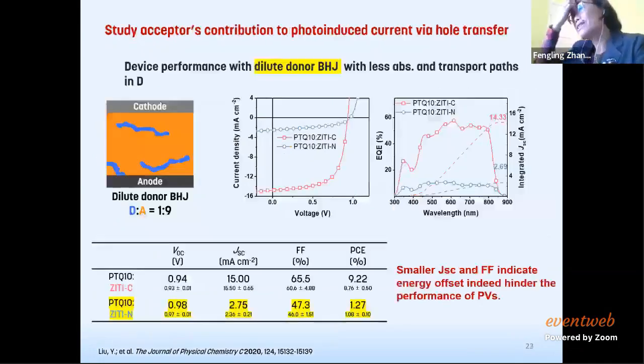So then we try to understand how the acceptor contributes to charge generation via hole transfer. Therefore, we make a device. Actually, we wanted to make a bilayer device, but the student in Beijing told us it's not possible with solution processing, because the top layer will dissolve the bottom layer. Then we thought, okay, if we can't make a pure bilayer device, maybe we can make a dilute donor device to decrease the impact from the donor and amplify the contribution from the acceptor. So it's closer to a bilayer.